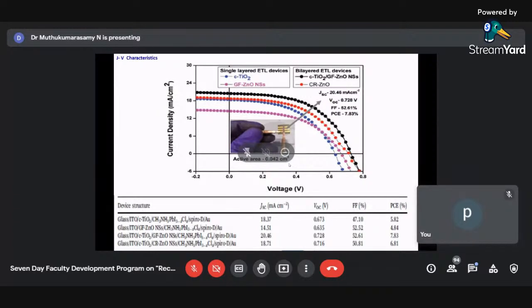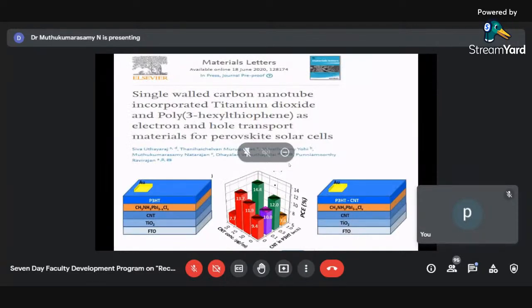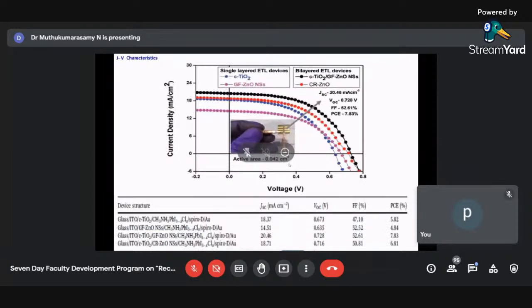You can see we got 20.46. The maximum current shown by even very good researchers is 25, 26. We got nearly 20. The only thing, as I told you, is that we were having problems with the open circuit voltage and the fill factor. We were able to achieve an efficiency of nearly 7.83%, 8%.